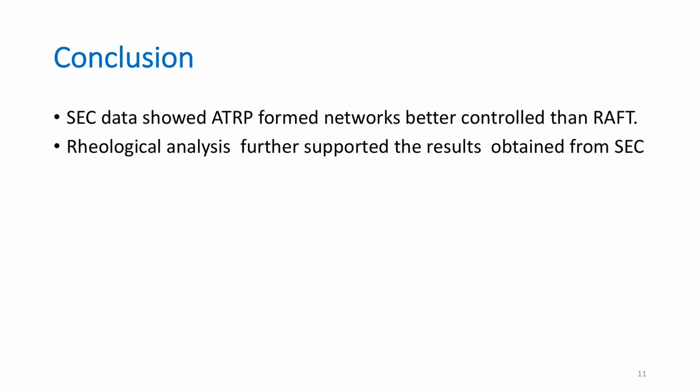So as a conclusion, our size exclusion chromatography data showed that the ATRP technique forms networks better controlled than the RAFT technique, and our rheological analysis further supported the results from the size exclusion chromatography, which finally concludes that ATRP gives more homogeneous networks than the RAFT polymerization technique.